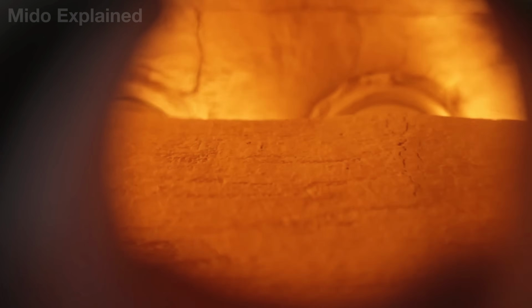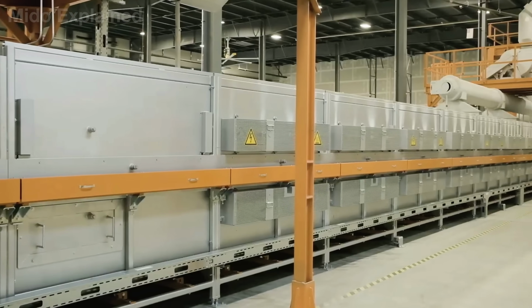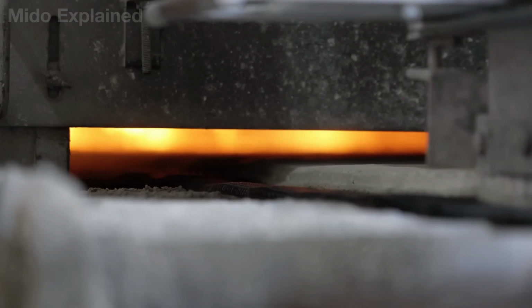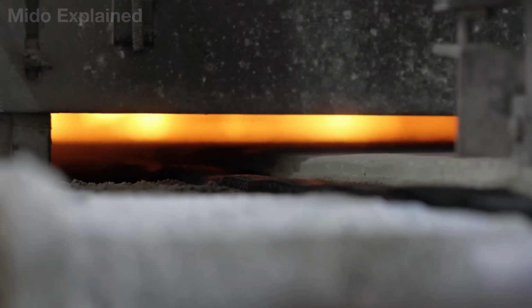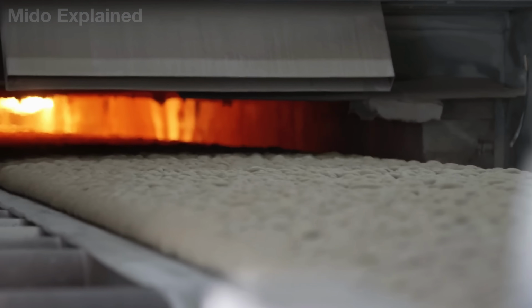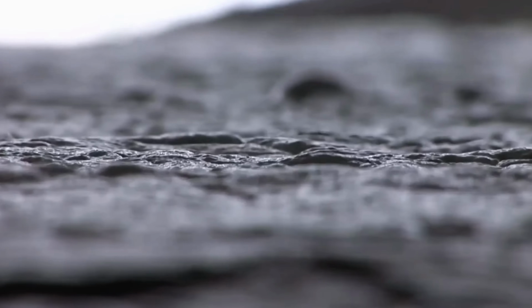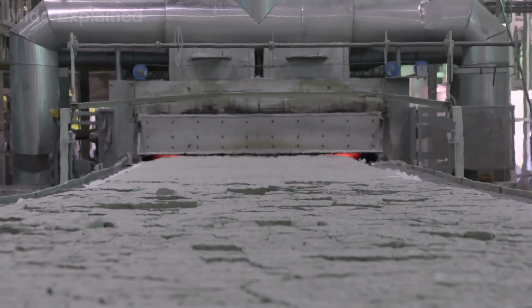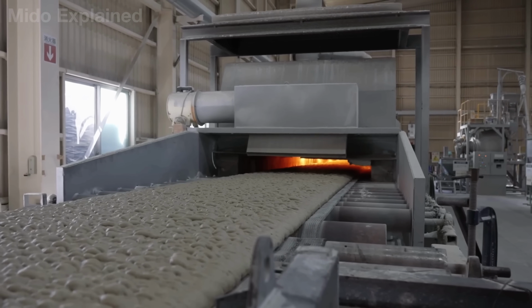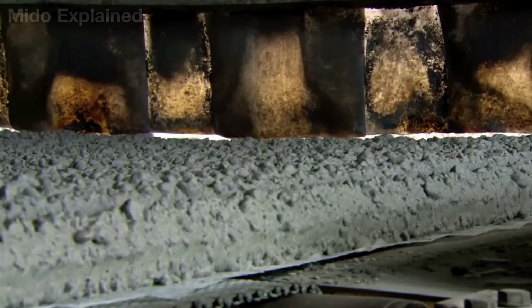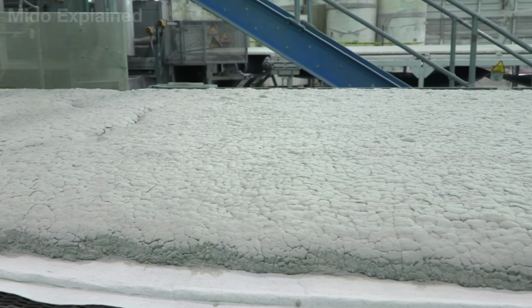Inside the furnace, the temperature gradually rises to approximately 1,700 degrees Fahrenheit. At this temperature, the glass particles do not completely melt but become soft and viscous, like a thick mass of honey slowly flowing out. Simultaneously, pre-mixed carbon or coke particles begin to react and release CO2 and other gases within the material. While the glass is in this soft state, these gas bubbles cannot escape. Instead, they are trapped within the material and gradually expand, forming millions of closed air pockets distributed throughout the structure.